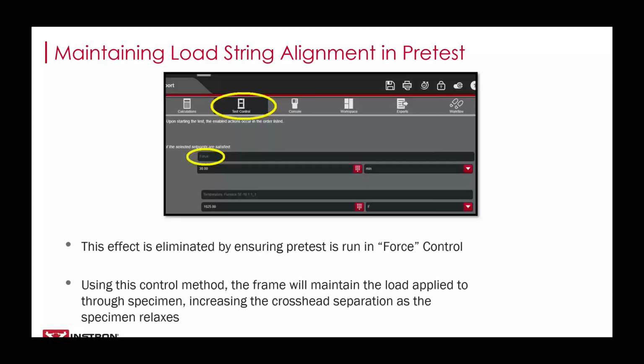Next slide, please. So to maintain alignment, what's kind of happening behind the scenes and how can your testing software actually help you prevent chances for misalignment? This is a screenshot from an elevated temperature test method set up in Blue Hill Universal. The way we configure our preload settings is we set the preload to force control. This means your load string will be held at a constant force for a set duration of time or until your temperature soaking criteria has been met. This ensures even if the load string deforms, the crosshead will automatically adjust to ensure it's maintaining that force that you specified. Next slide, please.